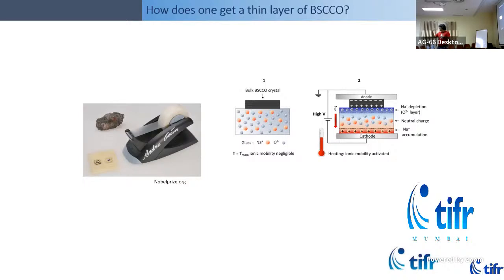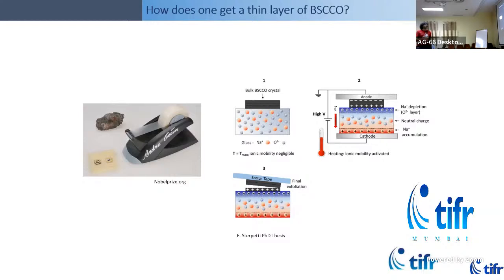And we followed somebody else who actually first, I would say, invented this method for BSCCO. So you basically use some glass which has mobile ions inside it, sodium ions, typically soda glass, and you put the crystal on top, and then you apply a large voltage. And what it does is it bonds weakly the material and the glass because of the application of the voltage and opposite polarity. That when you cleave off the mother crystal, you get very thin layers, a few atoms thick layers.